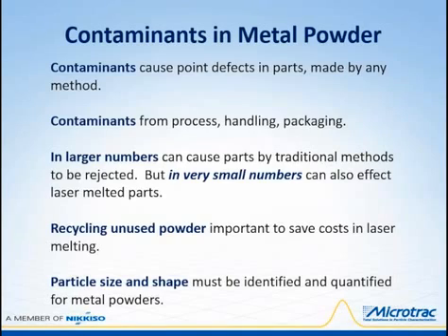Recycling unused powder per pass is important in laser melting to reduce cost on high specialty alloys. The recycled stream has to be remeasured before using again until the powder is out of spec. Powder shape analysis is a very fast and accurate way to identify and quantify the proportion of contaminant particles in the feed material to the laser welder. Every recycled batch has to be first analyzed for its morphology.